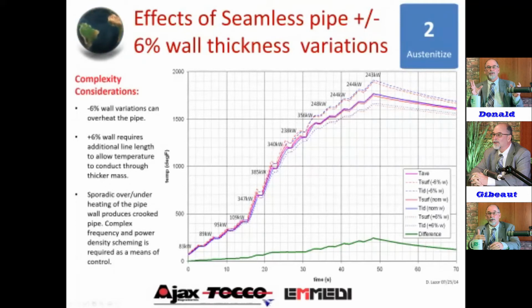And here is a delta T curve. Each one of these spikes on this curve is where there's an induction coil. And then here's the fall of the surface in the gap in between. And then it races up again. Then you get up to the magnetic Curie point here. And you can really see where we're pouring the coals to it with additional power density. The dotted lines are showing the maximum and minimum of the API spec on seamless tubing.